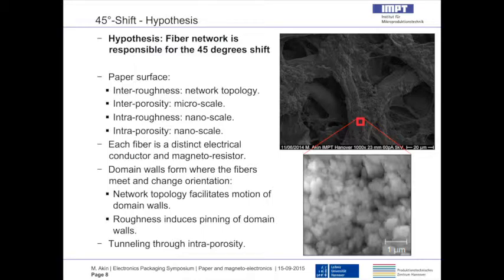And last, I would like to show that when zooming in, this is an AFM measurement of the fiber, you see a porosity and you see the nanopores. And once that surface is coated by a magnetic material, for example permalloy, if all conditions are set, you may have a tunneling of electrons through that intraporosity, basically the nanoscale or fiber level pores.